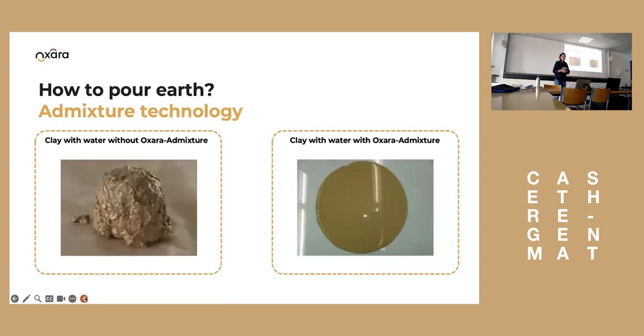So this is the idea, and how does it work? The idea behind the admixture technology is that if you have clay and you mix it with a certain amount of water, you can reach a plastic state, as on the left side of the picture. And of course, you could reach the state on the right-hand side by just adding more water, but you don't want to use that much more water, because if you add more water to reach fluidity, you also have a much higher shrinkage and you introduce too much water. And later it cracks and loses its strength. So the idea is to do that change from plastic to liquid with an admixture and not by adding water.